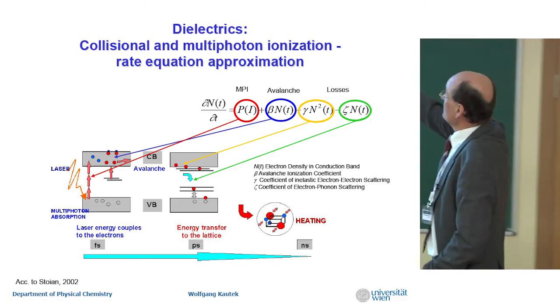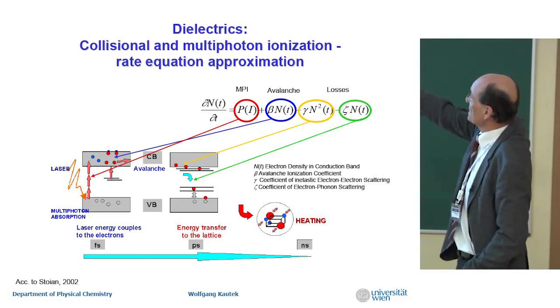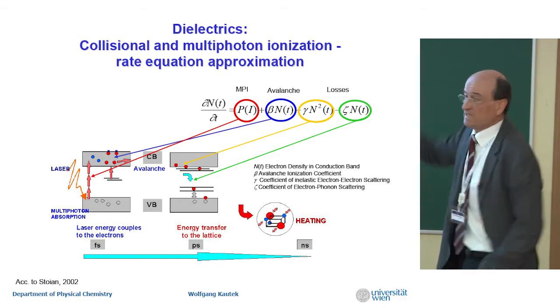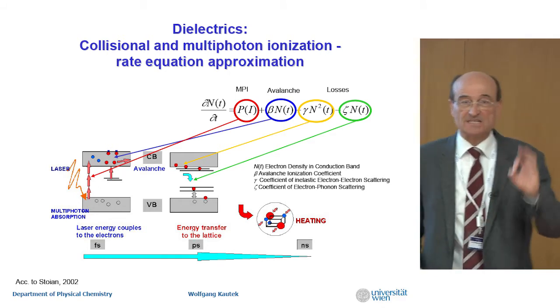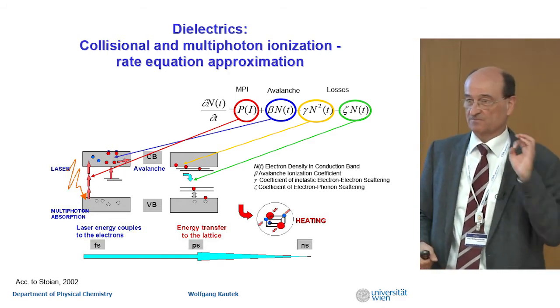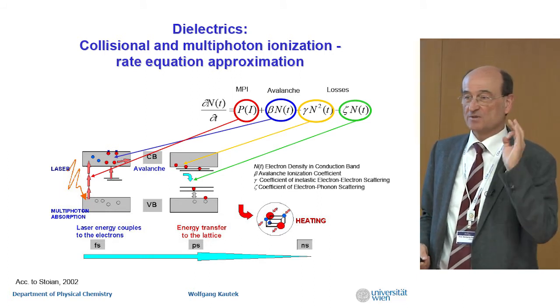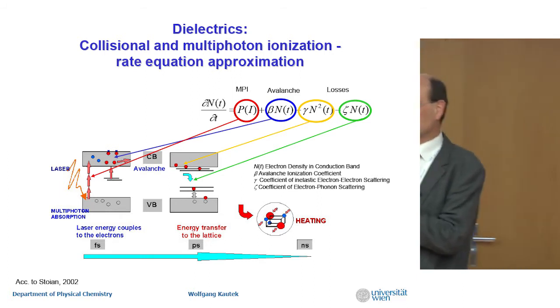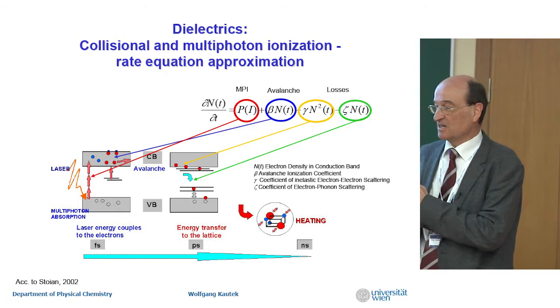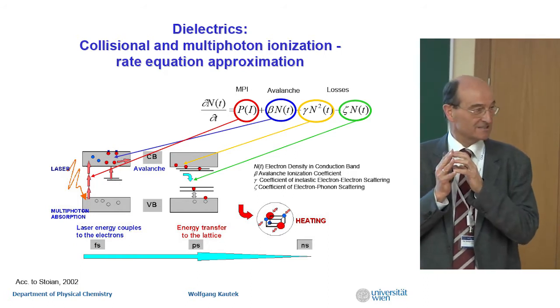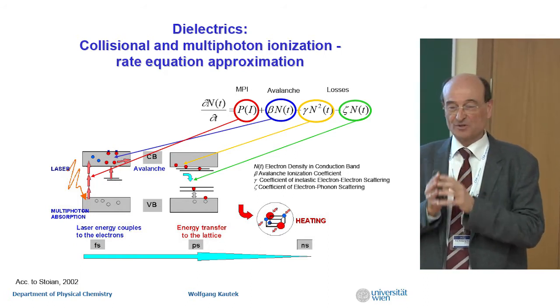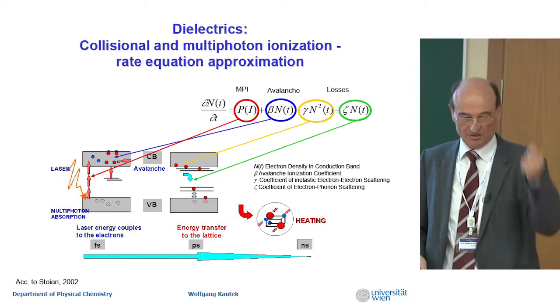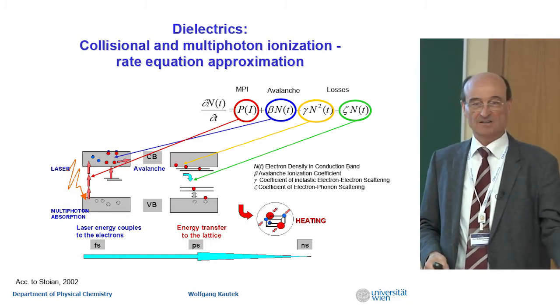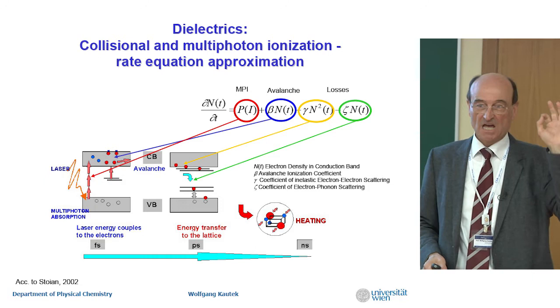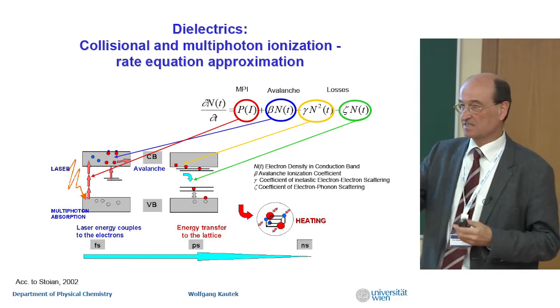So when we increase this term here, we increase a deterministic excitation process. Deterministic. And remember, the best result in ablation of a dielectric was at highest intensities. So the multi-photon excitation is a deterministic process. You can determine the result, the excitation.